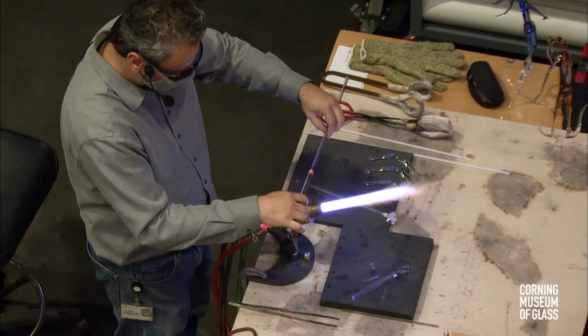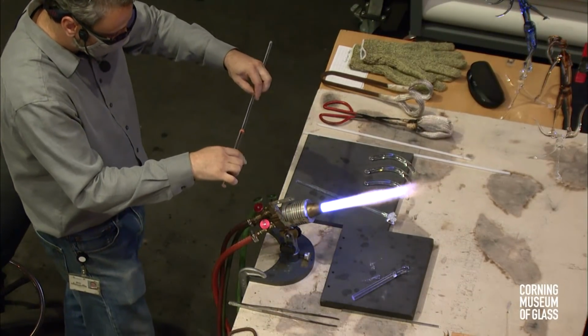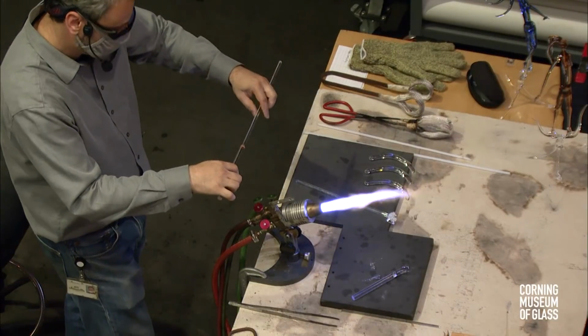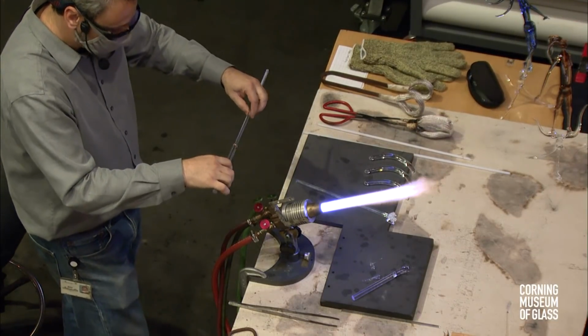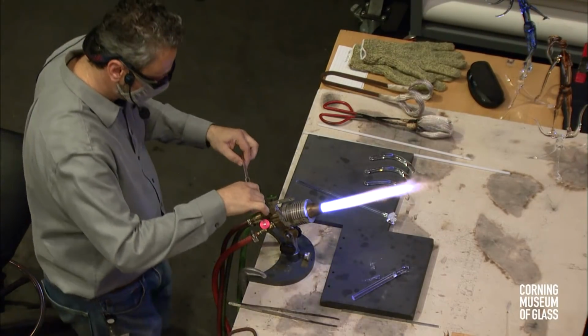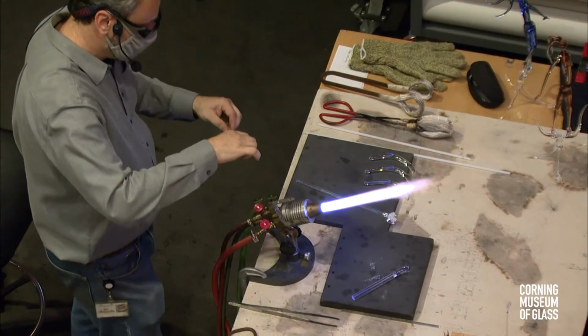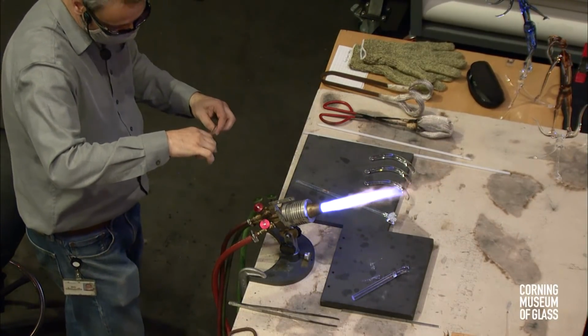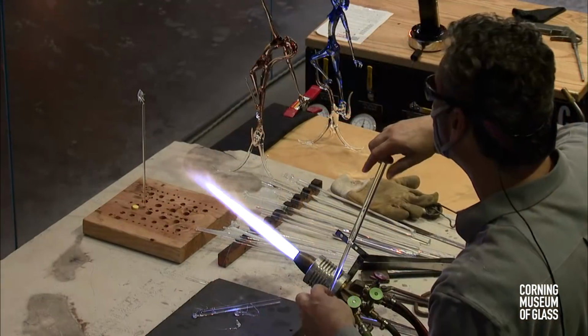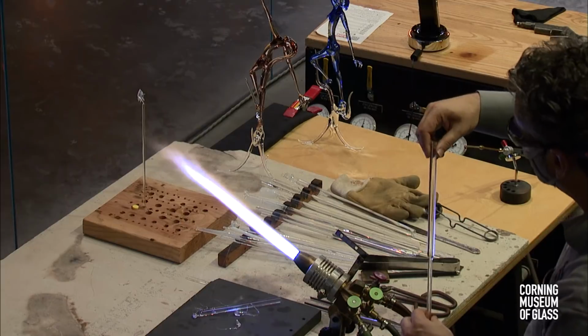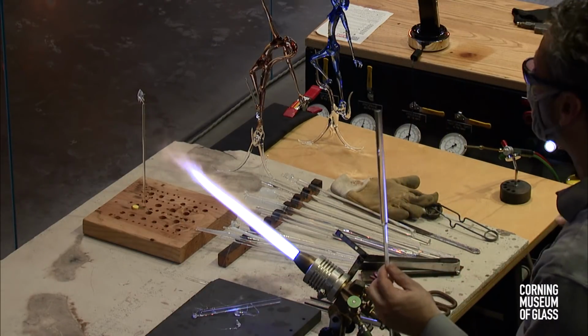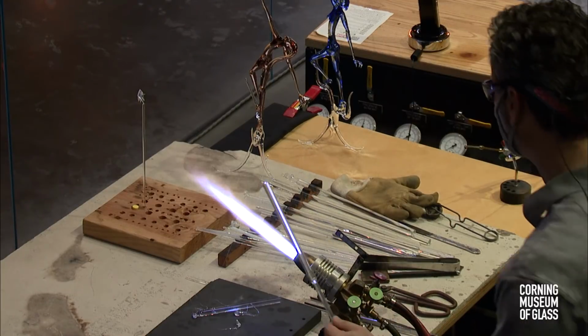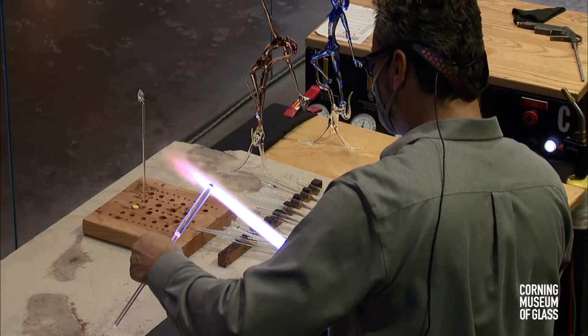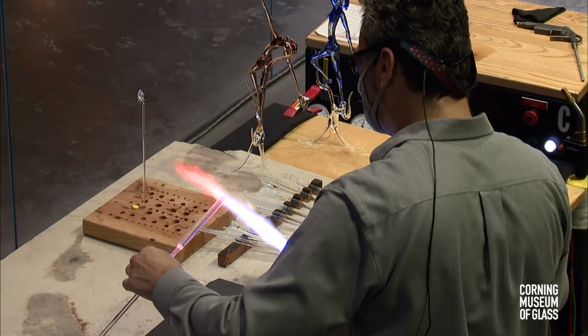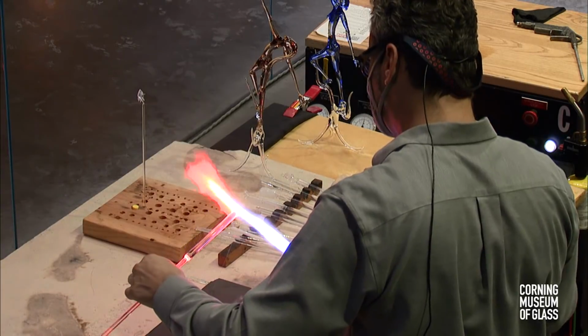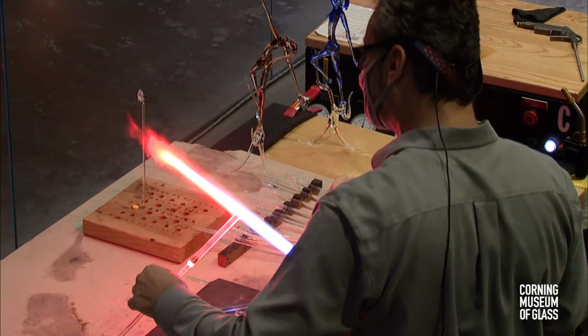So I just attach some of the thicker rod to a narrower handle. Makes it easier to handle, go figure. And I'm going to round off the other end of the rod. When you heat into a broken edge of glass with a torch, it tends to boil and bubble. What we typically think of as a broken edge, we think it's just that one sharp edge, but there are actually a whole bunch of little micro fractures that run along that. So if you just heat into that micro fractured edge, you start to seal in some of those micro fractures and they bubble. They turn into bubbles. You're actually sealing an air pocket.